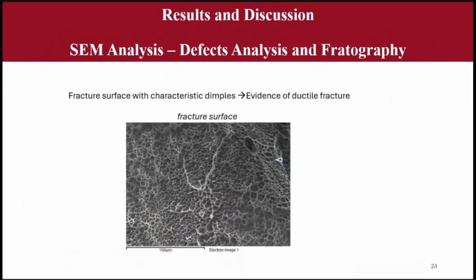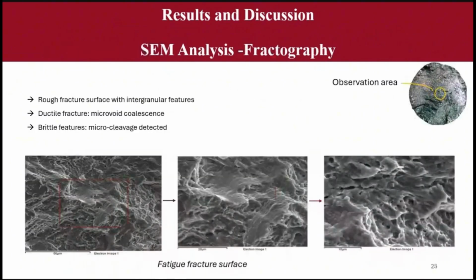Here is the fracture surface with characteristic dimples that give evidence of ductile fracture. Here we can observe the rough fracture surface with intergranular features. We can see the square that I put there. Ductile fracture with microvoid coalescence and brittle fracture with micro-cleavage are detected.